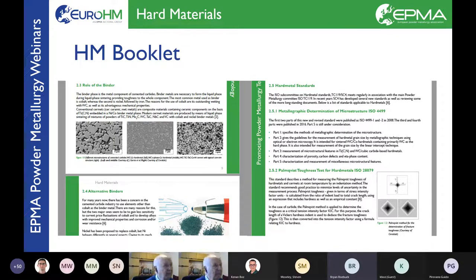For example, firstly, we can use the binder phase to tailor the thermal properties, and we can do this by changing the volume fraction, the chemistry, or the size. And size is important because in terms of thermal properties, interfaces are very important. And clearly, the smaller the size of the binder phase, the more interfaces we have. And that is a significant effect on the thermal properties. Secondly, by altering the chemistry, that is by adding other transition metals than cobalt, the binder can significantly affect the corrosion properties and other forms of degradation too.